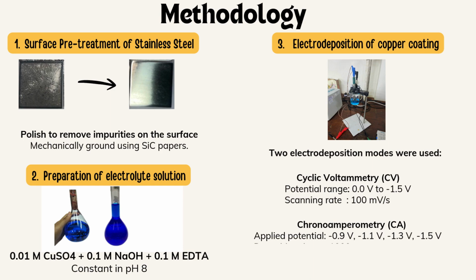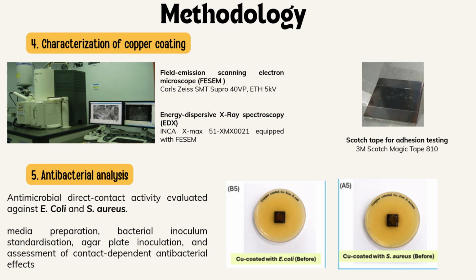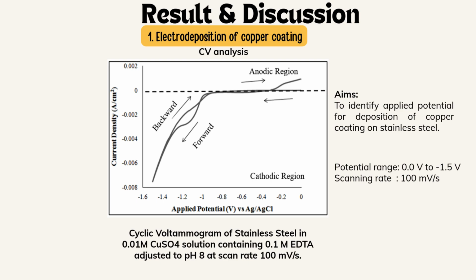And next is the electrodeposition of copper coating by using two different modes, which are cyclic voltammetry or CV and chronoamperometry or CA in a 3-electrode setup. The next method is the characterization of copper coating by using FESEM, EDX, and Scotch tape for adhesion tests. And lastly is antibacterial analysis to assess the direct killing effect of antimicrobial activity against S. aureus and E. coli.